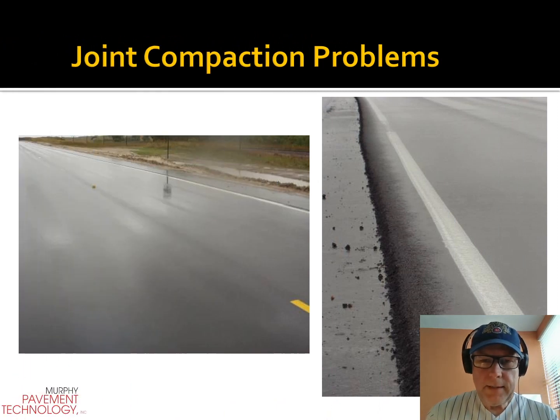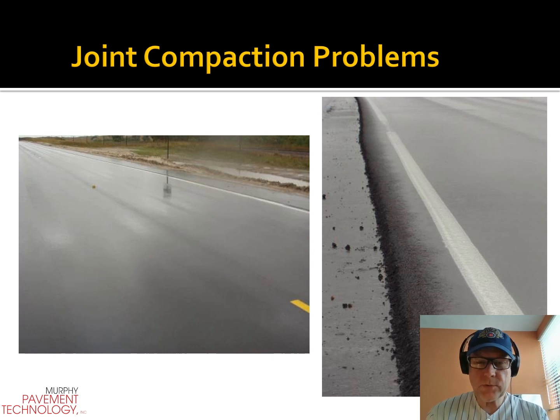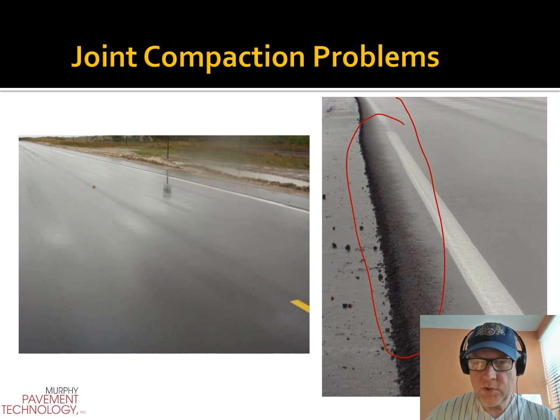The asphalt on the left is a roadway that shows exceptional mat compaction, the middle of the roadway. On the right is a photo that shows incredibly poor compaction at the joint. It's a visual. You can see it gets darker and that the moisture is traveling through it. In this case, I'd be inclined to suggest that that asphalt 6 inches wide be saw cut off, removed, and replaced. Otherwise, it's going to cause a problem on our athletic asphalt with low density, high moisture retention, and therefore failure of the coatings.